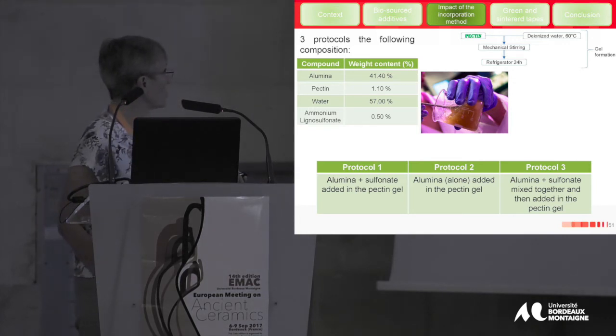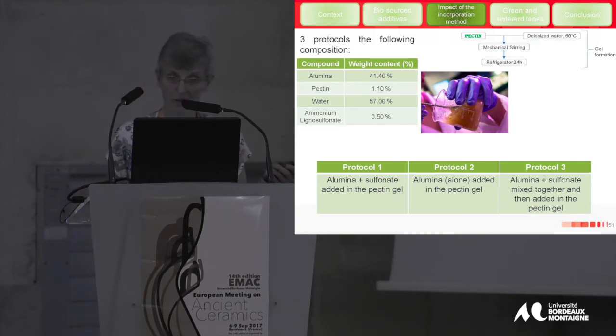Second protocol was to add alumina alone in the gel, and the third protocol was to first mix the alumina with the dispersant and then add it in the pectin gel.